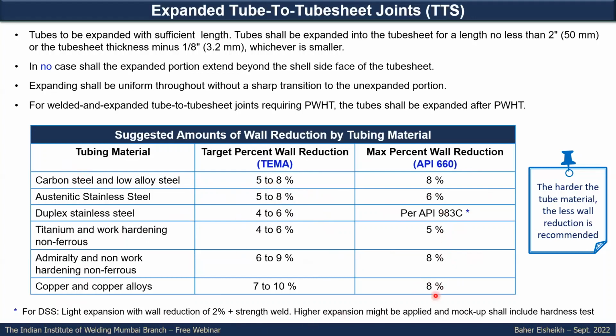For the duplex stainless steel, we can see in API 983C, for the use of duplex stainless steel, they are recommending light expansion up to 2% only, plus strength weld, meaning you cannot apply only the expansion. But again, this is a technical report. This is a good engineering practice. We saw for some applications that up to 5 and 6% was applied in duplex stainless steel in many cases.